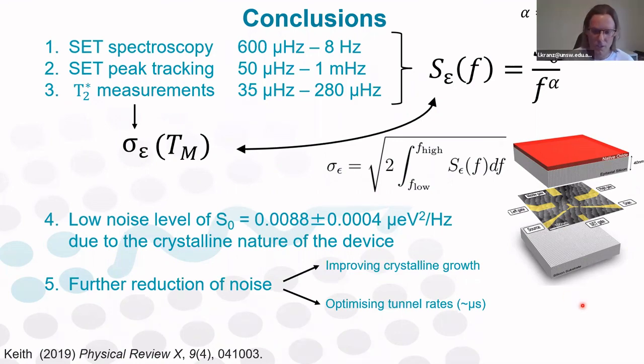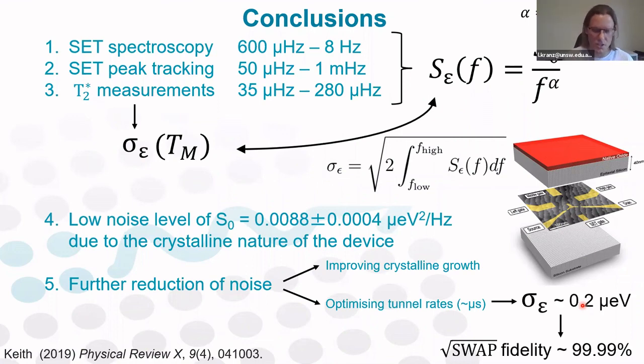And secondly, we recognize that going forward, it's going to be important to execute quantum algorithms really quickly. So we think we can achieve this by speeding up our readout. From our previous results, we know we can execute single-shot readout at around the microsecond scale. That was achieved in different devices. But we estimate that by combining low charge noise characteristics with this really fast readout, we can possibly achieve a really small integrated noise of below 1 micro eV. And we can also estimate that with realistic values for noise, two-qubit gate fidelities as high as 99.99% are in reach